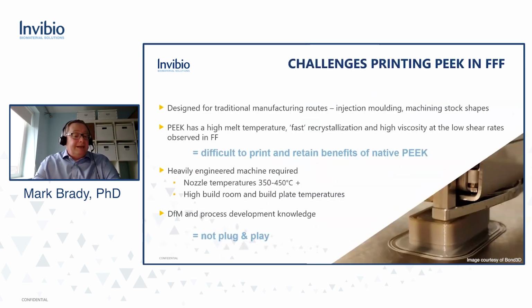But printing with PEEK isn't a slam dunk. It was originally designed, PEEK, for traditional manufacturing routes. Its high melt temperature of around 340 degrees, fast crystallization speed, and relatively high viscosity at the low shear rates observed in fused filament fabrication make it very challenging to retain the benefits of the native PEEK.